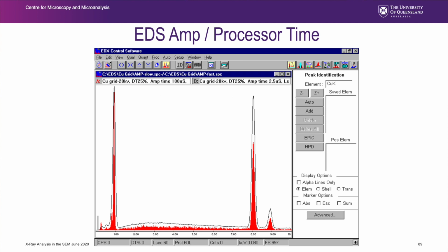And this is copper measured at 20 kV. I adjusted the spot size, so both of them have 25% dead time, and I have in black a quick amp time, and in red, the solid graph, I have a slow amp time. One is for throughput, one is for spectral resolution.